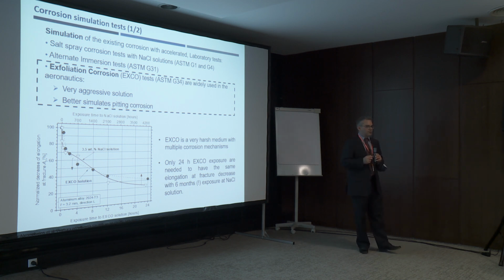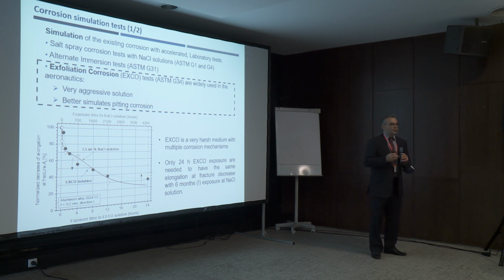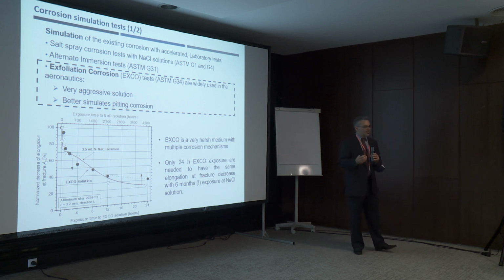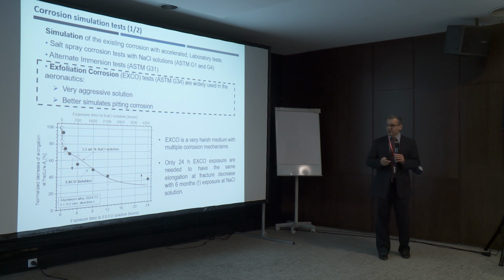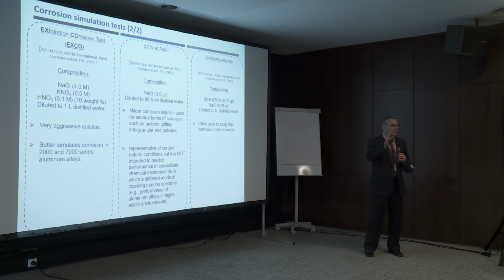So the purpose of this work is to investigate which is the most appropriate corrosion solution, and to investigate the corrosion mechanisms that should be involved in these new alloys. To this end, we have tested 3 different solutions. The classical one, according to G34, is highly susceptible to exfoliation. Exfoliation means that cracking and exfoliation takes place after some corrosion exposure times. The typical one with sodium chloride. And we investigate another one that is most promising, the Harrison one, that could be found also mainly for magnesium, but we have evidence that it might be most appropriate for identifying the corrosion mechanisms.